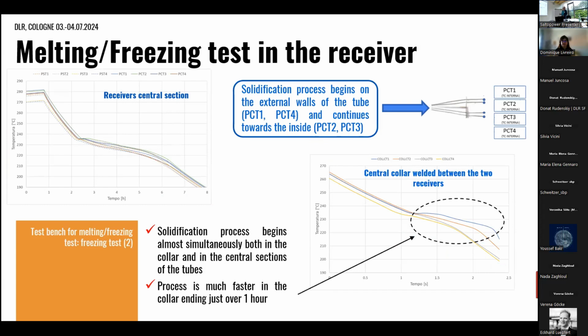here are the temperatures of the thermocouples positioned in the central section of the receiver. In this case, the two receivers start the phase change more or less simultaneously, and go more or less at an equal trend. Also, in this case, you can see that the solidification starts on the external walls, that is the coolest part, and then proceeds towards the inside of the tube.